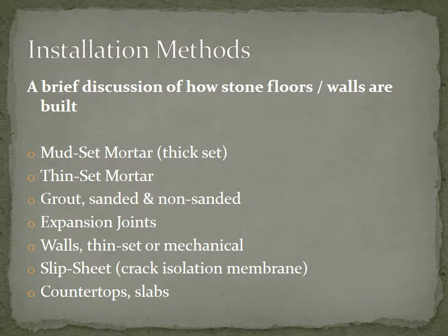Okay, now the grout for installation, there's two types, sanded or non-sanded, or sometimes they call it unsanded. Unsanded grout is for grout joints an eighth of an inch or less. Sanded grout is for grout joints an eighth of an inch or larger. The sand keeps the grout from sagging when it's in a larger area, and it keeps it from cracking as it shrinks and as it dries.